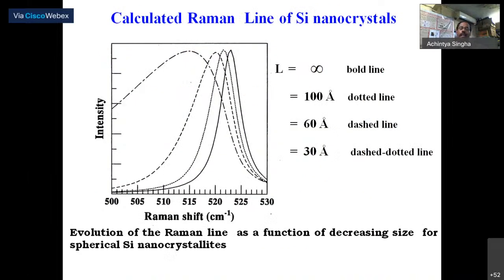So you can see here the calculated Raman line of a silicon nanocrystal, and the solid line is for silicon bulk. You can see the Raman spectrum is a symmetrical Raman peak, and as we decrease the size, due to the confinement effect, we can see some asymmetry on the lower energy side. You can see how the asymmetry increases as we decrease the size. So from this calculation and experimental data, you can get the size of the particle from the Raman measurement. So go next.